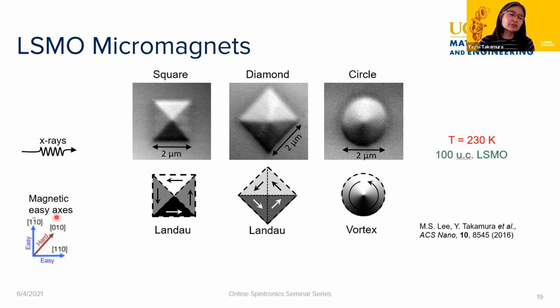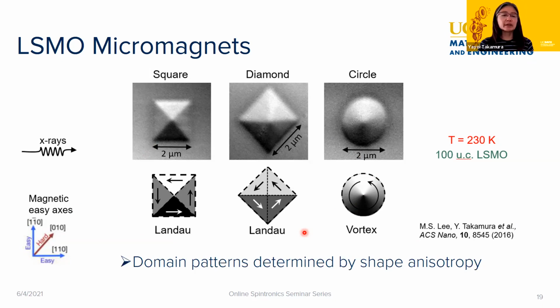And then what I want you to always reference is the direction of the X-rays and the direction of the magnetic easy axes for this film. For LSMO on strontium titanate substrates, the easy axes are actually the 110 family directions and not the 010 family. And so what we get is Landau or vortex structure domains. Nothing unexpected, right? It's basically shape anisotropy dominating at this particular condition.